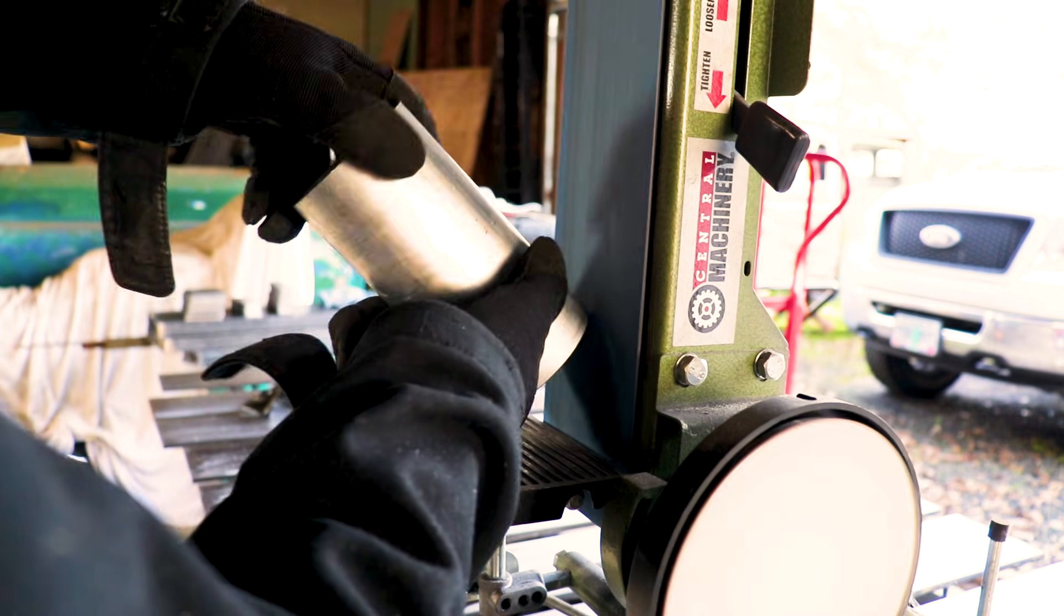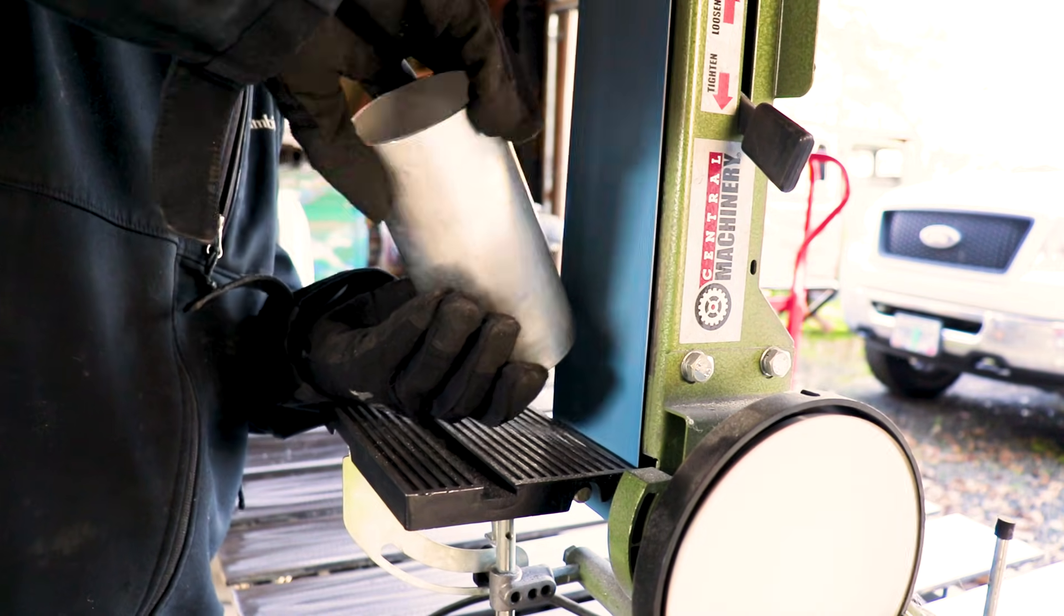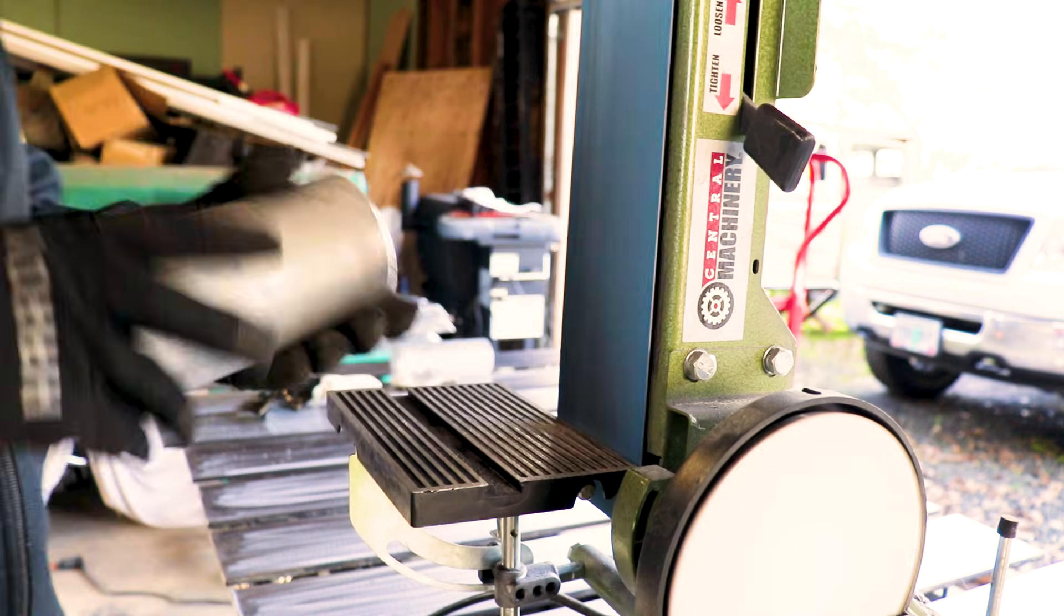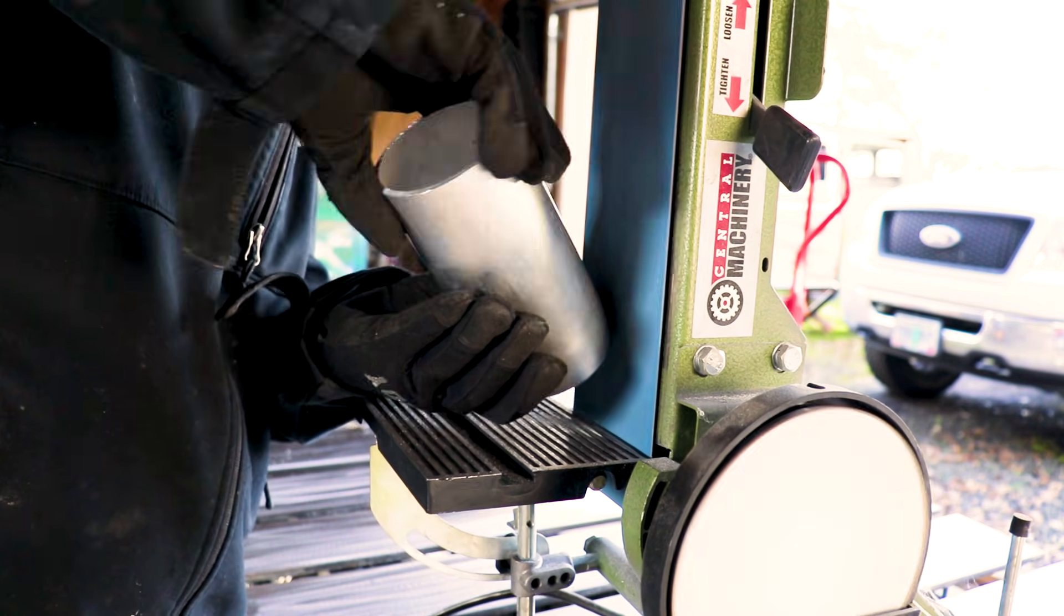When I'm welding pipe I like to bevel it at about a 45 degree angle unless it's some real thick like schedule 80, and then I'll do about 37 and a half degrees like most people.